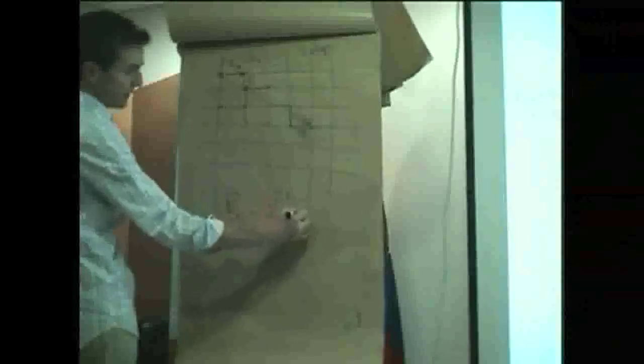I want to know the distance between this point and this final point here. I call R0 this average distance. Every single vector here has an index, which I call A1, A2, etc., and AN. These are vectors of length A, which is the size of a monomer. And I write that R0 is just equal to the sum from i equal 1 to i equal n of Ai. Very simple. And I want to know the average norm of this vector.